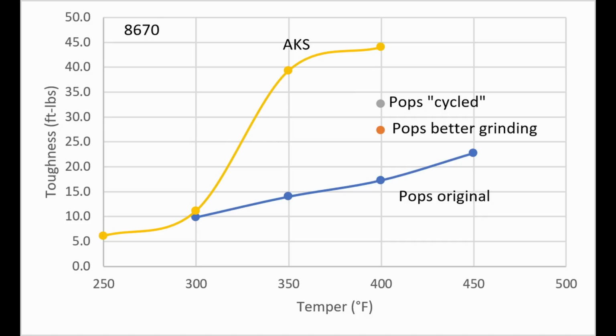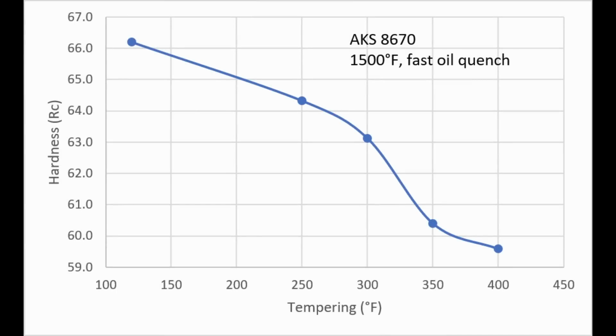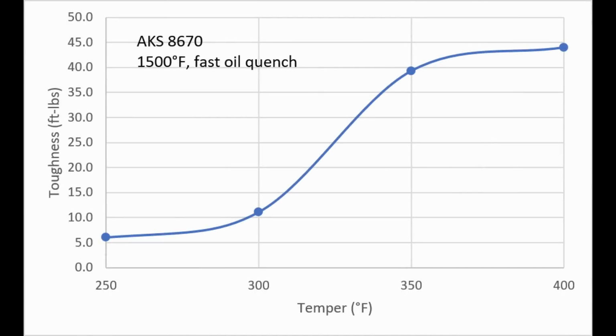And because we were worried that this was some kind of fluke, Warren and I heat treated and machined some new coupons with a range of tempering temperatures to see, what is the trend here? Why is this steel so much tougher? And we got a similar hardness curve to what we had with 15 and 20. And again, we saw a rapid increase in toughness by tempering at 350 to 400 instead of 300. So again, the trends are holding.